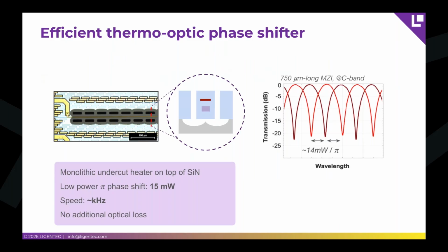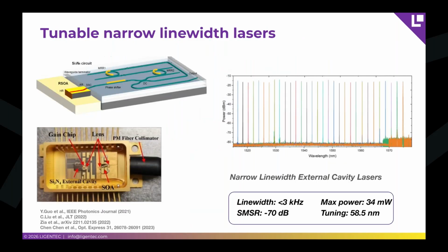efficient thermo-optic phase shifters. And one application that we can do with these excellent passive components is for example, a tunable narrow line width laser, where you integrate a 3-5 component like an RSOA together with a silicon nitride circuit and the heaters that act as phase shifters and tunable elements for the cavities. And with that we can reach kilohertz with maximum power outputs of tens of milliwatts and tuning ranges of tens of nanometers.